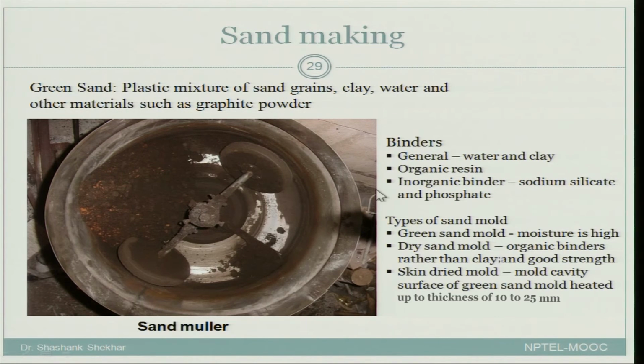Green sand mold is the one which has moisture. Since it has moisture, it is called green sand mold. Then there is dry sand mold, where, since you do not have moisture, you add something else, for example organic binders rather than clay and water. Then there are skin dried molds, where the mold cavity surface of a green sand mold is heated to form a strong layer up to a thickness of 10 to 25 millimeter.